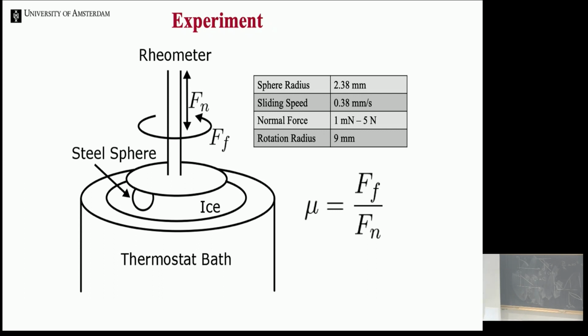Yeah, and so this is a variation on the rheometer theme, where instead of a bottom plate, I use a layer of ice, and instead of a top plate, I actually glue a steel sphere onto the plate at a known distance, and then I drag the steel sphere over the surface. And the nice thing of the rheometer is that it spans many orders of magnitude in speed and in force. And so what I end up with, if I measure the torque, I can deduce the frictional force, the force necessary to drag my sphere over the ice, and the rheometer immediately gives me the normal force, because it has a normal force transducer on the axis of the upper tool.